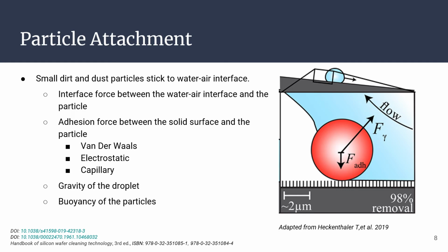Static electricity tends to be higher on solid surfaces at lower humidity, and as static electricity can be either attractive or repulsive, when both van der Waals and electrostatic forces are present, the particle will stick to the surface if the sum of the two forces is positive. The overall force of adhesion is lowered as the surface roughness increases. Therefore, nanotextured surfaces are better for self-cleaning purposes.